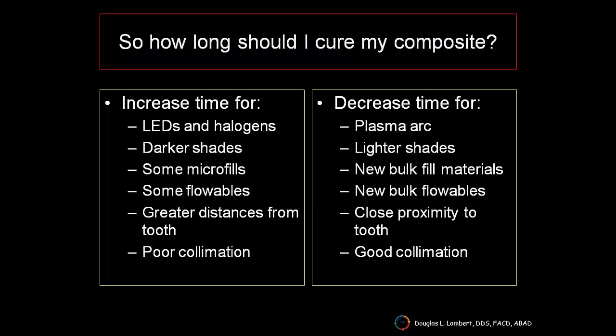Well, basically you want to look at a couple of parameters. There's reason to believe that we should increase our curing times for some LEDs and definitely for some of the older halogens, if you're still using a halogen light. The darker shaded composites bear that out in the literature. Some microfills, some flowables, again, I would check with the manufacturer to see if they fall in that category. The further distance you are from the tooth, you may want to increase the curing time. And if you have a poorly collimated light beam, you're going to have to rely on your research on the light that you have to see if you have a good one or a bad one, you definitely may have to increase your curing time.